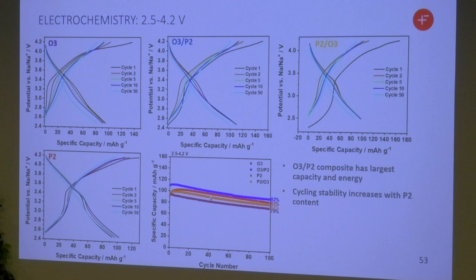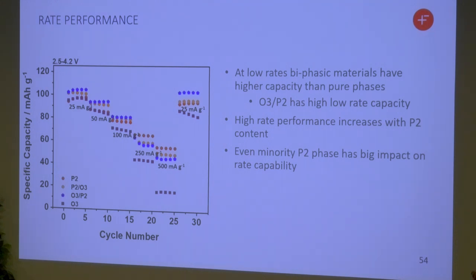So they all cycle against sodium quite well. It turns out that the composite material, which has quite a lot of O3 and some P2, has the highest capacity, has the highest energy. They become more stable with cycling as you increase the amount of P2, which fits with what I said. What's interesting is if we start varying the rate at which we cycle, the O3 material does really badly at fast charge and discharge. But we don't need to put a huge amount of P2 in there, and it improves hugely. So that gives us a lot of flexibility in how we design our materials.